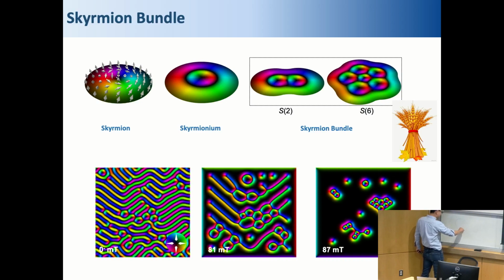So this is a configuration from center to the peripheral. If you just focus on the change of nz, this equals the change of cosine theta. So this is responsible for this part. But then you're traversing around this configuration, and you see how your spin rotates, how your in-plane spin configuration rotates. If your in-plane spin configuration delta phi rotates by n times 2 pi, then your topological charge will be n. But for most conventional skyrmions, when you traverse around the skyrmion, this will just rotate by an angle of 2 pi. So you only have plus or minus 1. But this is another way to realize a high Q state.